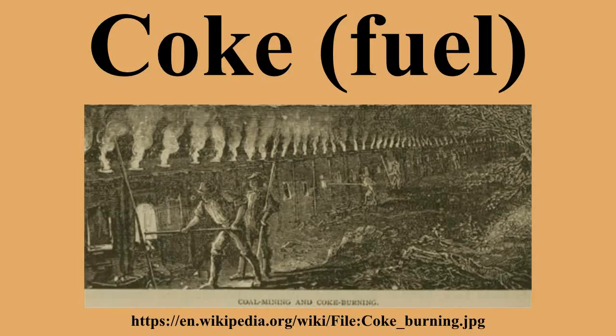Production. Volatile constituents of the coal, including water, coal gas, and coal tar, are driven off by baking in an airless furnace or oven at temperatures as high as 2000 degrees Celsius, but usually around 1000 to 1100 degrees Celsius. This fuses together the fixed carbon and residual ash. Some facilities have by-product coking ovens in which the volatile hydrocarbons are mainly used after purification in a separate combustion process to generate energy. Non-by-product coking furnaces burn the hydrocarbon gases produced by the coke-making process to drive the carbonization process. This is an older method, but is still being used for new construction.